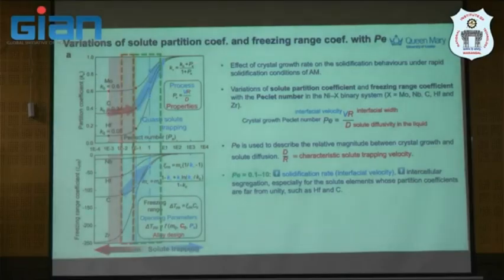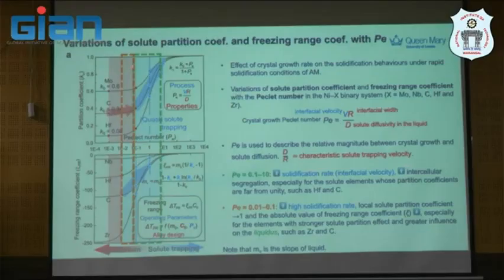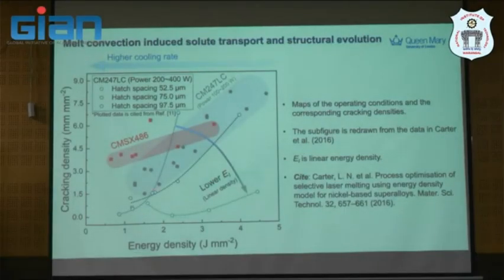And then if you're talking about near equilibrium, if you have a high solidification rate as well, if you are in this zone, it's still trapping as well. Your freezing range will change. So it will be decreasing, such as the solute profile that contributes to this, such as zirconium and carbon. So what this means is that the process parameter is so important that we know in CM247 LC, if you change your hatch spacing, power, energy, you will actually get different crack density based on the previous study here in the LPBF.